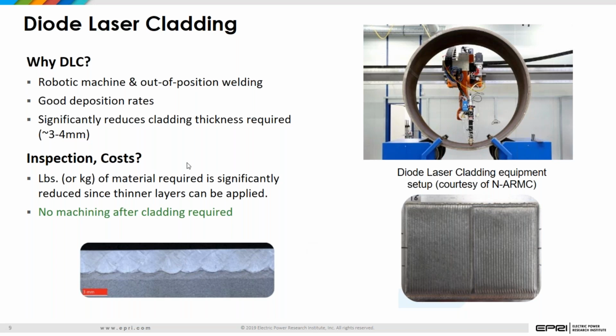We think that we can get this to where we can apply it where you may not have to do any machining of the cladding itself, such that you can get better inspection or ease of inspection. Again, I want to point out one of the key attributes of this is that it requires a lot less material in terms of overall application. So volumetrically, you're not putting down as much. If you're putting down a nickel-based material, you certainly want to minimize the amount of material that you apply to reduce overall cost.